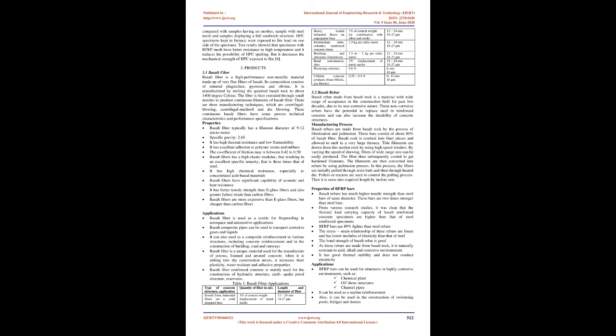HPC specimens kept in the furnace were exposed to fire load on one side of the specimen. Test results showed that specimens with BFRP mesh have better resistance to high temperature and it reduces the possibility of HPC spalling. But it decreases the mechanical strength of HPC exposed to fire. 3. Products. 3.1 Basalt fiber.